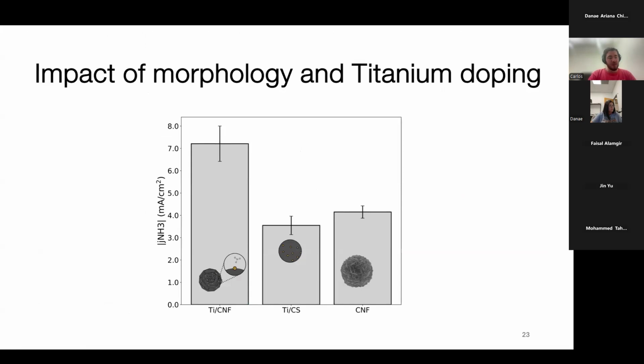And then finally, for the impact of the morphology and the titanium doping, we compare titanium doped carbon nanoflowers with titanium doped carbon spheres and just pure carbon nanoflowers. What we see is that we are able to double the ammonia production current density. So we're doubling the yield and the rates at which we're producing ammonia, compared to both the titanium doped carbon spheres and the undoped carbon nanoflowers. So this indicates the importance of having both a titanium doping and titanium sites, but also the kind of improvements that we can get from having the enhanced surface area that the carbon nanoflowers provide.